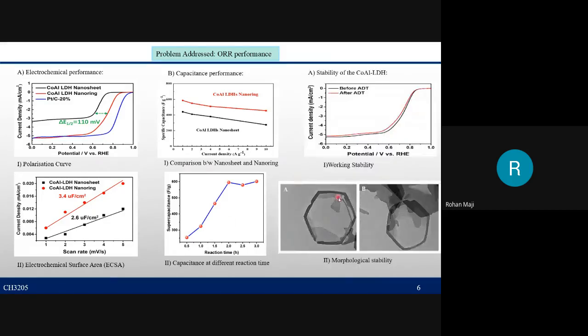The electrocatalytic stability of the cobalt aluminum LDH nanoring was characterized to study the working stability of the nanoring, and we can see the result. Here, the result before and after the ADT, which is the accelerated durability test, shows that the nanoring has insignificant activity decay. And also, if we see the morphology, no obvious morphological or structural damage could be observed, indicating the stability of the nanoring.